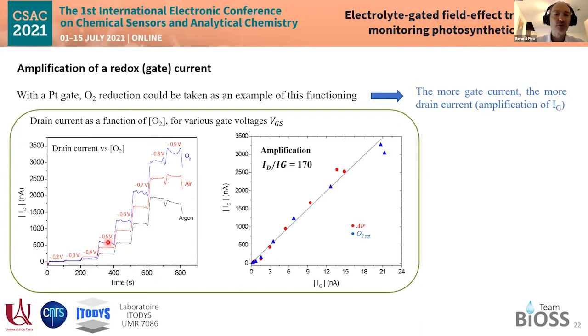the current starts to flow through the drain, and starts also to flow through the gate, of course, but I didn't show the gate current. As soon as we start to reduce oxygen on the gate, there is an amplification factor, that is the ratio between the drain current and the gate current, which is, I would say, constant, of around more than 100. It could be 170 here, up to 1000, actually, depending on the geometry of the device. So we could amplify that redox reaction, oxygen reduction, through the device.